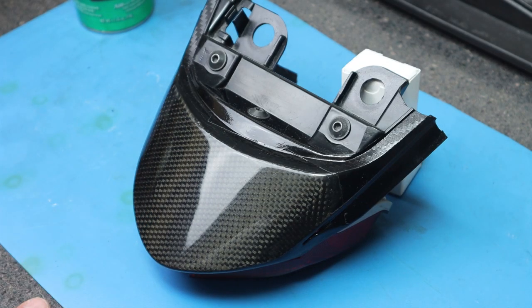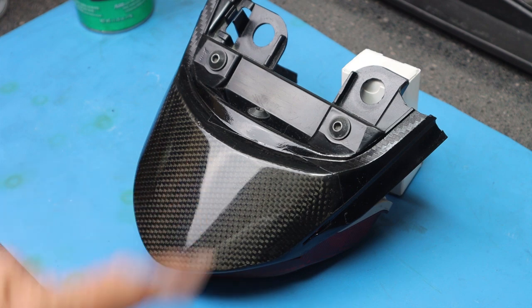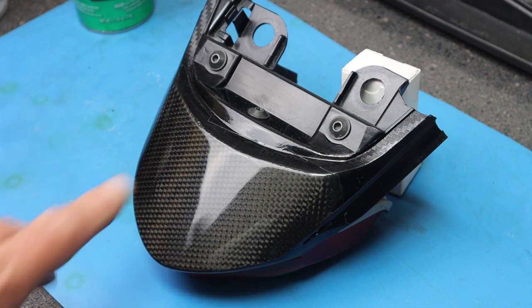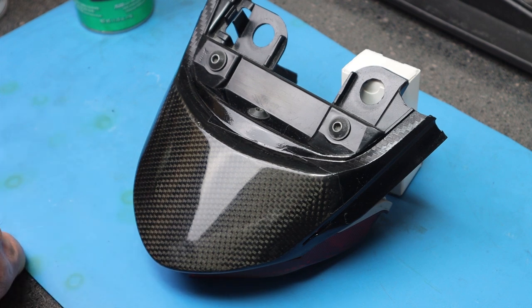So again, I had trouble with the Rust-Oleum Painters Touch paint. It shrunk down over the carbon weave and almost made it to where you could actually see the weave through the finish — I didn't like that. I sanded it off, redid it with the Spar Urethane, at least four or five coats, let it sit for two days. Then you can start your sanding routine: 400, 800, 1200, 2000, and then come in with your polishing compounds — first the UltraCut Compound and then an Ultra Finishing Polish. As you can see, the finish is really smooth with no pits, holes, or bumps. I wanted to make this as a follow-up video so that in case you ran into or run into the same problem, you'll know how to fix that.